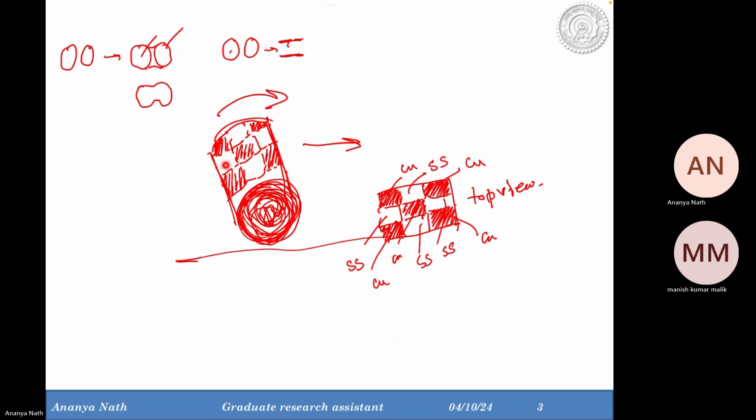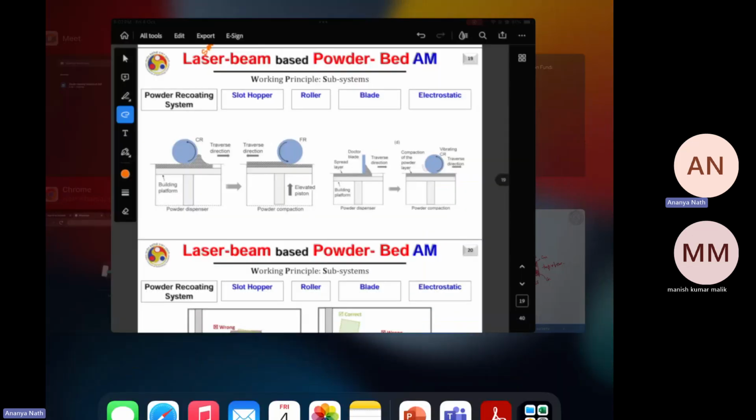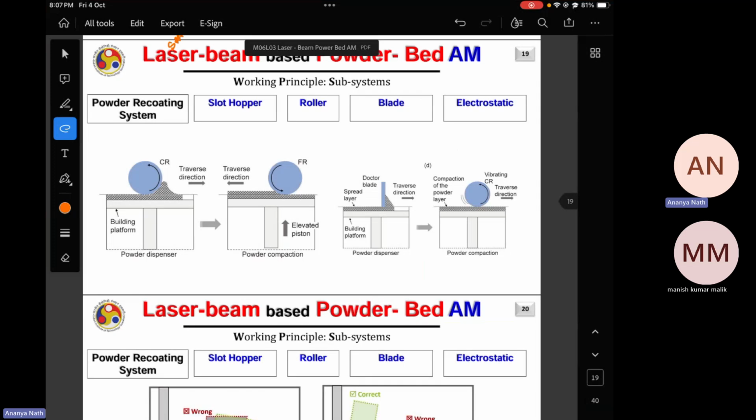these parts, okay, this white part will get electrostatically charged by another type of charging with other values, and now it will only attract the stainless steel. So the stainless steel is getting attached to the roller, and when the roller is rolling over the build plate, it will spread the powder on these white parts, and then the laser will consolidate the white parts. So this is how you can really print multimaterial with the help of this type of electrostatically charged roller type